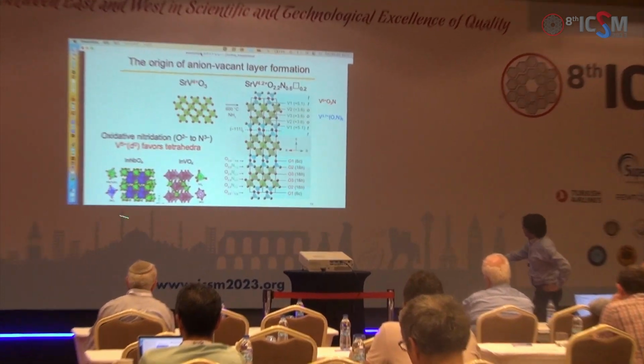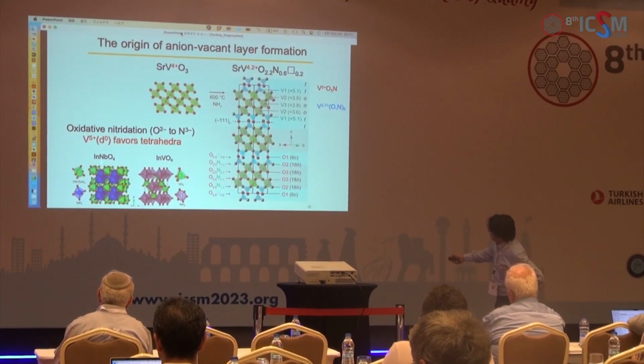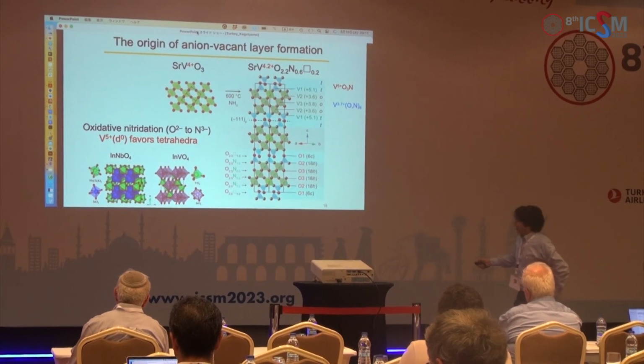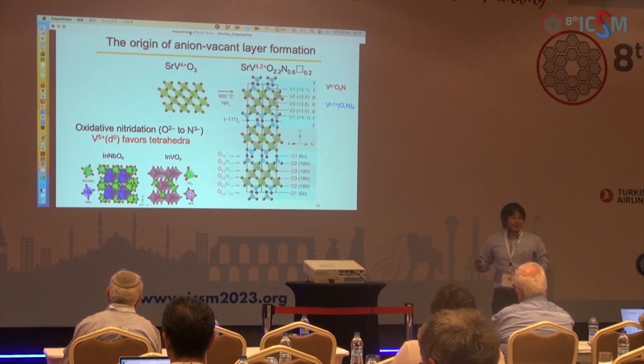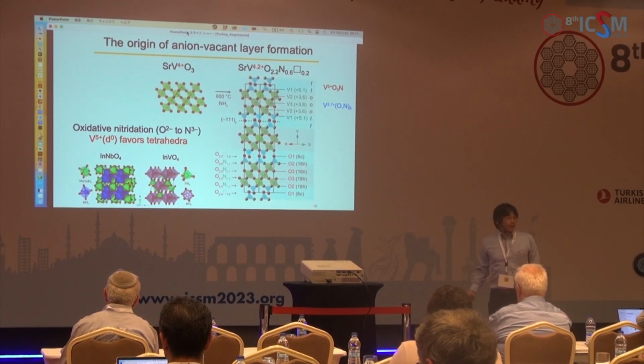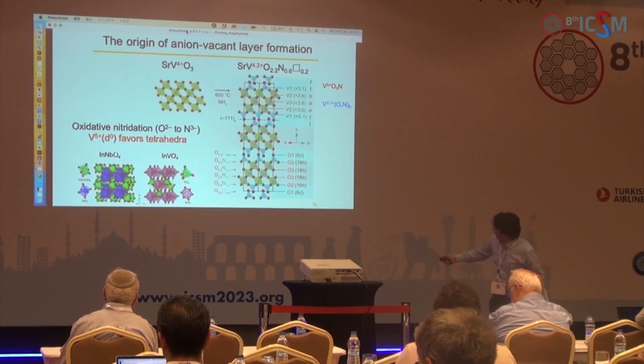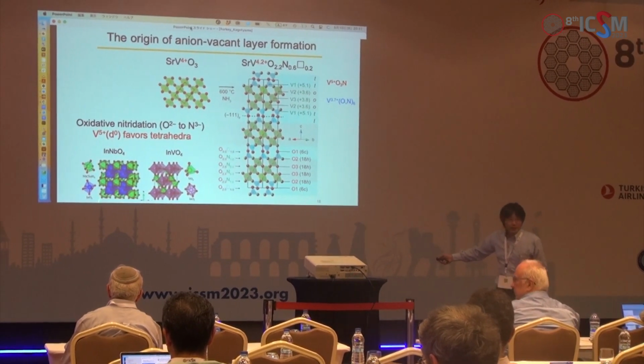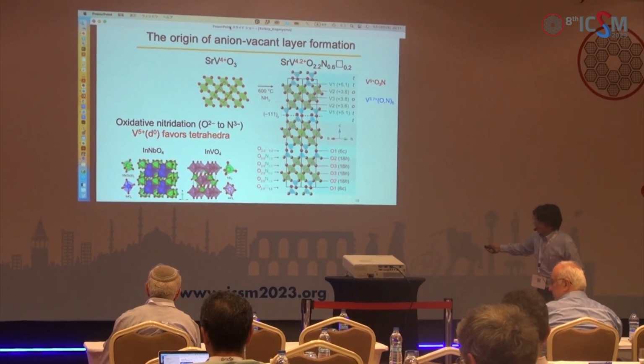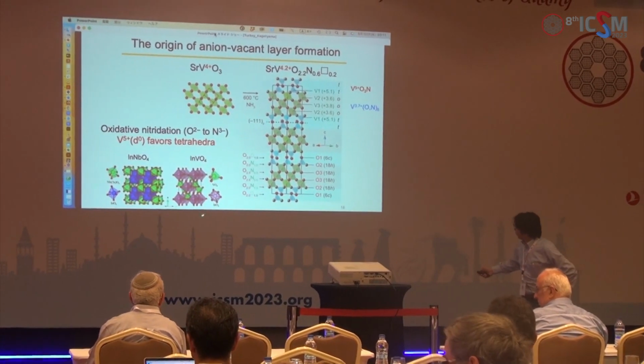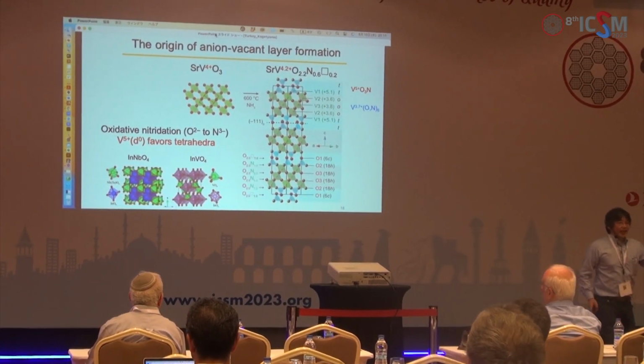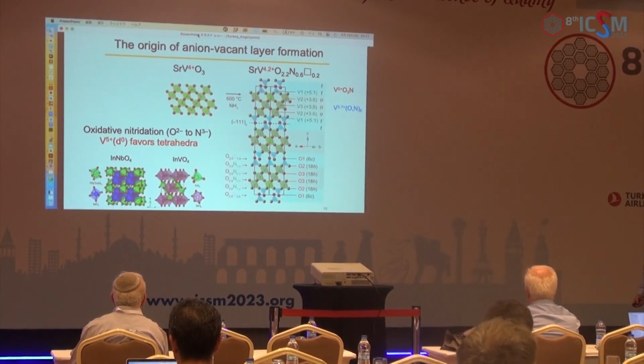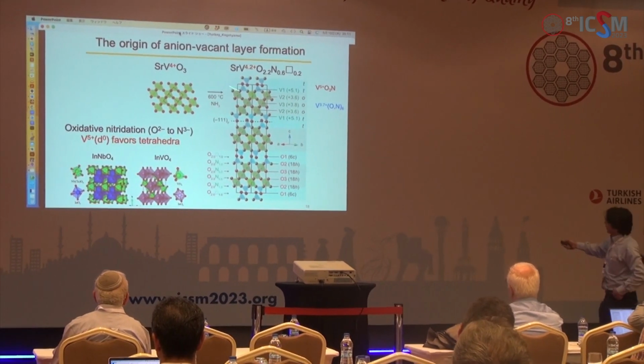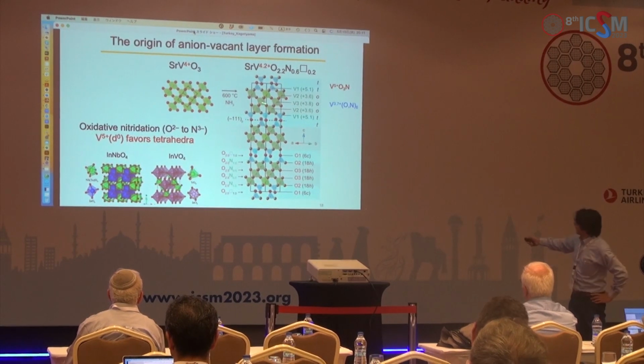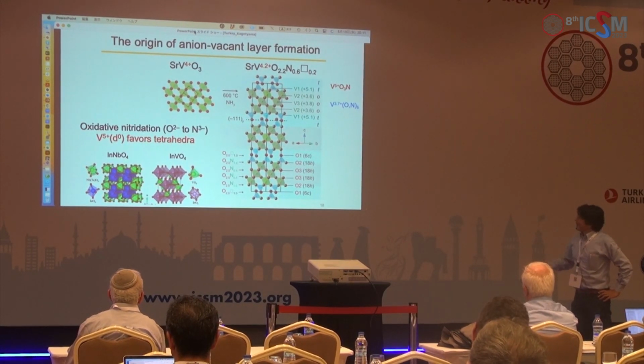But as you can see in this material, in the VO4, vanadium 5+ prefers to have a tetrahedral coordination, as you can see from this one. For niobium, in this case, it is octahedral coordination, but vanadium 5+ wants to have a tetrahedral coordination. Actually, this oxidative anion-exchange reaction gives rise to such a layering in this way. Okay.